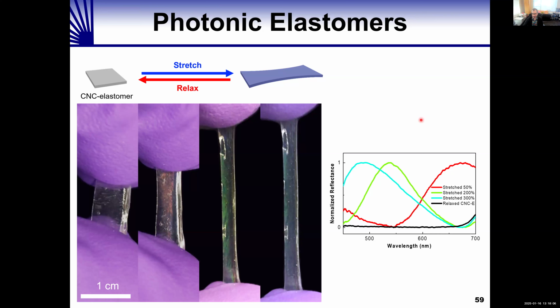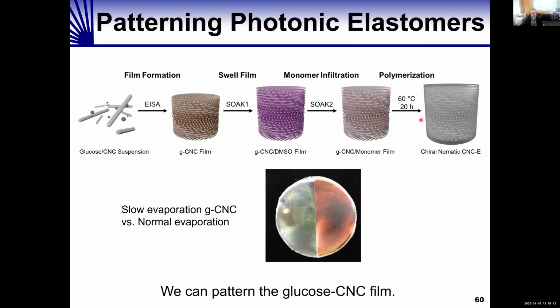One neat thing with this process is that our starting glucose cellulose nanocrystal film can be patterned. So we've got some cute tricks to pattern these films. In this case, we made a patterned film where the right side has a helical pitch corresponding to red light, and the left side has a helical pitch corresponding closer to green light.